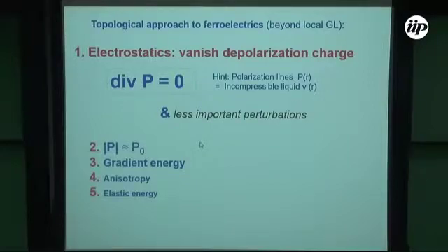And this is also the answer to some of your questions, thanks Pasha. So actually, epsilon is a constant. And as I told you, the depolarization energy is huge. It's enormously huge. So the answer is that the system tries to do everything to avoid the charges. All other energies are much less. So in principle, at least from my experience, there is some hierarchy in the energies. And first, the system is always trying to have the situation without charge. So qualitatively, and I will show you the results after, the system always tries to arrange itself to have divergence of P equal to 0. That's, I think, the nodal field that Pasha mentioned.